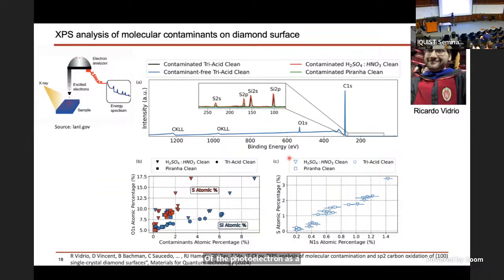And most of the time, you're only looking at the large features, which is okay, fine. You're dealing with diamonds, so you have this carbon 1s peak, and then you're dealing with an oxidized surface, so you have this O1s peak. And then if you really zoom in, you actually start seeing all these impurities. So you have silicon, sulfur. A lot of that just comes from breathing on your sample sometimes during processing.